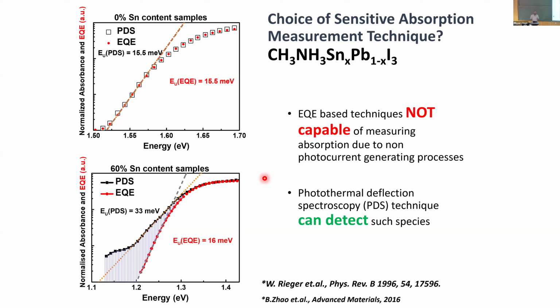But if you have a system where you want to measure photocurrent, when does photocurrent happen? When do you measure photocurrent in the external circuit? When you have both a free electron and a free hole coming out of the material or device. So if you have doping, you have a fixed ion and a carrier, and this free carrier absorbed that photon—it just went up in energy and then relaxed. So no extra carrier was generated, and you cannot measure photocurrent.